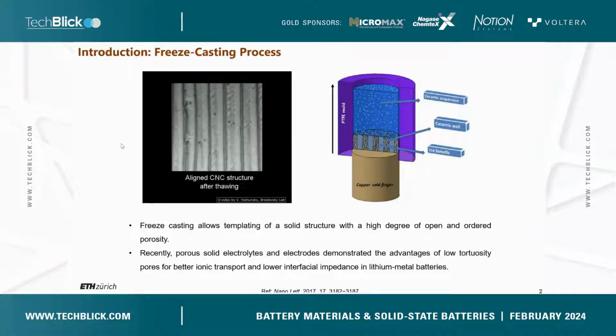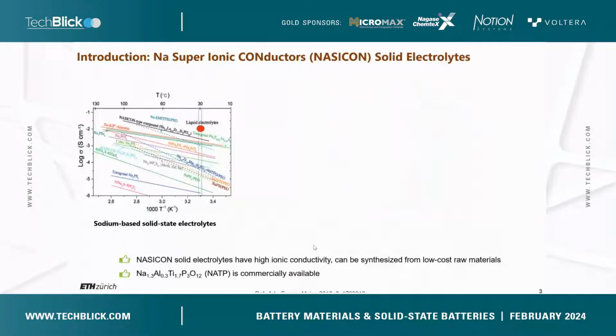So why is freeze casting important for the battery field? Because it was recently published that some of the lithium metal battery electrolytes have advantages from these low tortuosity porous scaffolds, which enable better ionic transport and provide lower interfacial resistance to the movement of lithium ions. And hence I decided to explore this for sodium metal battery electrolytes.